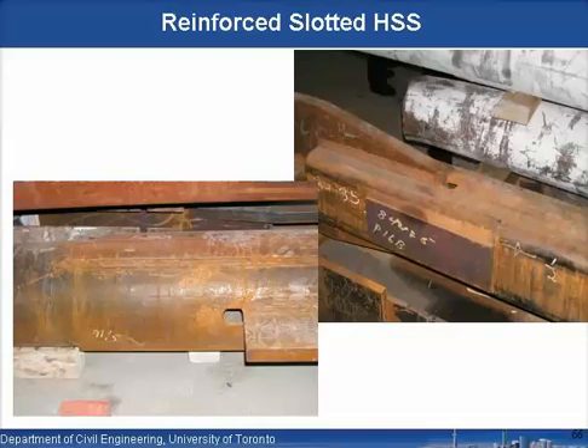And here you can see the popularity of using square hollow section braces over circular hollow section braces for these seismic applications, because when you do reinforce in this manner, you put the patch plate, the reinforcing plate, onto a flat surface, and if you keep the plate width within the flat width of the square hollow section, you can just fillet weld along the edges before you encounter the corners of the hollow section. Here, more complicated of course, because you have to have it sitting on the round of the circular hollow section. So that's what it would end up looking like after we've reinforced it.